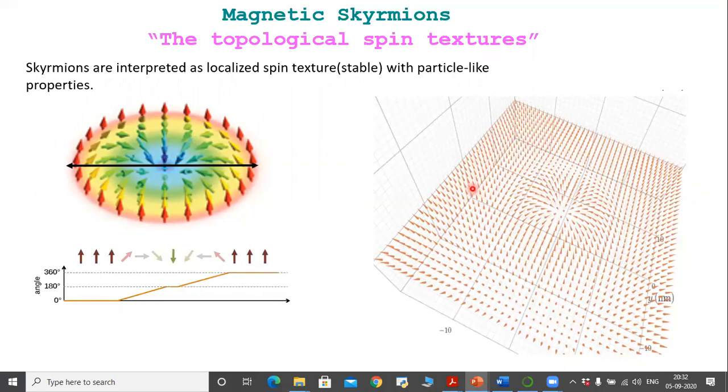If you look at the dynamics of the magnetization, you get an equation where m is the magnetization direction, and dm/dt is equal to two terms. The first is the torque-like term, which makes the dipole moments rotate, and the second is the damping-like term, which relaxes the dipole moment to the applied magnetic field. The picture is just like the phase space diagram of a damped harmonic oscillator.